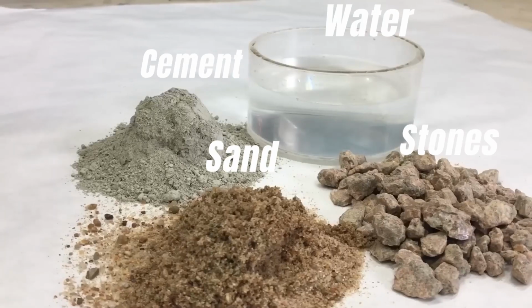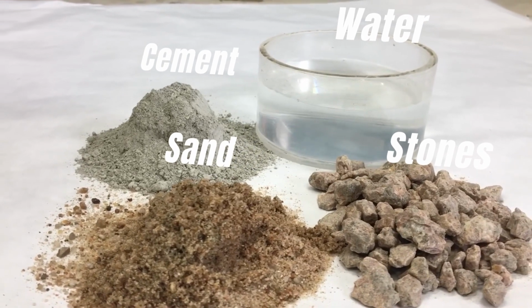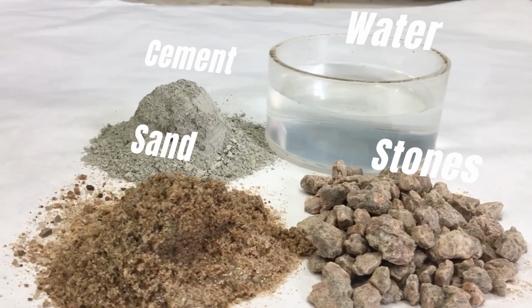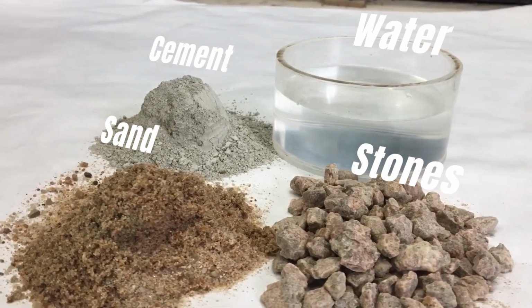That is to say, a proper ratio of active and inert components in the coal is one of the prerequisites for producing good coke. Therefore, we should not consider the inertinite component to be a bad thing in coal. It is analogous to the pebbles or aggregate in concrete, with the active components being the cement. It acts as the aggregate. In this sense, every material component in coal has its necessity and rationale for existence. This is because to produce qualified coke, there must be an appropriate proportion of active and inert components.